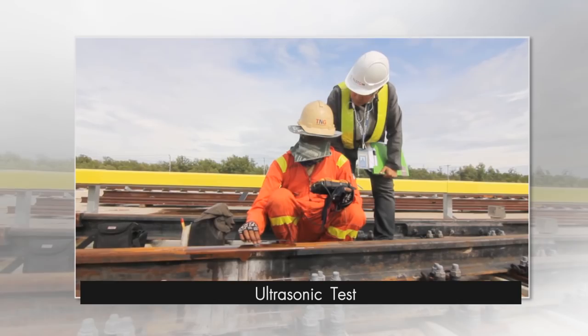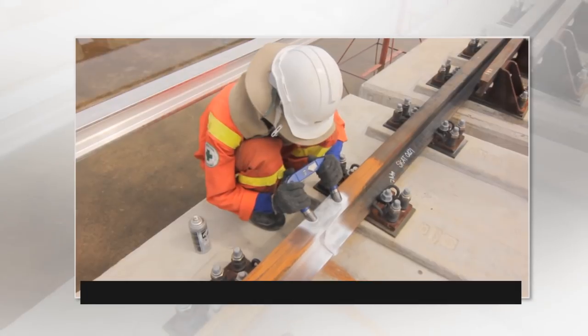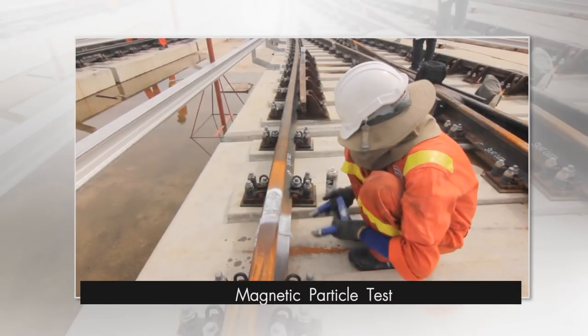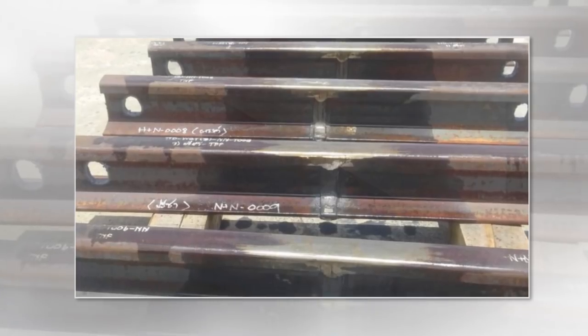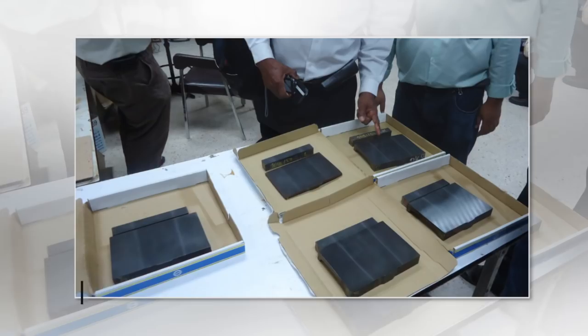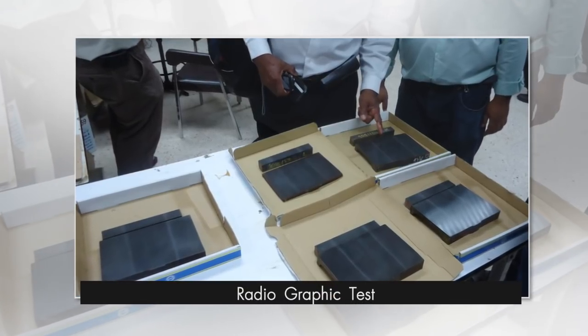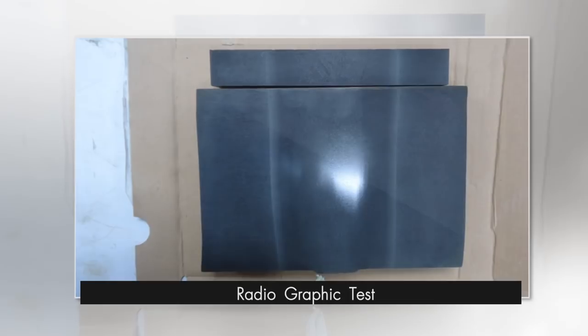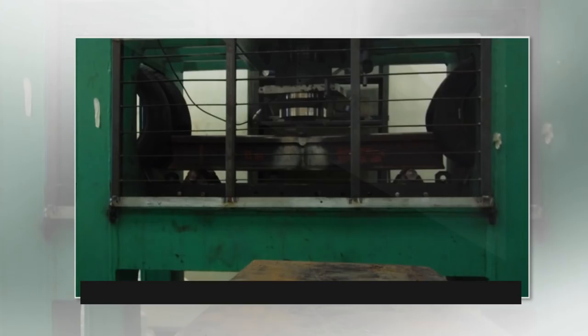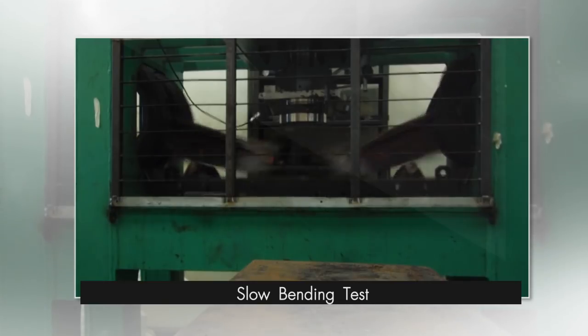Inspecting every welded joint using ultrasonic and magnetic particle test. After every 500 welded joints, submitting samples of welded joints to be thoroughly tested in a laboratory using radiographic test, and to be tested for durability using slow bending test.